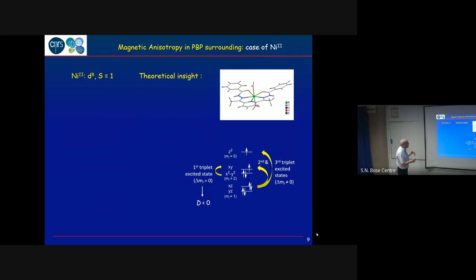Let's take just a few examples to illustrate that. For instance, if you take nickel(II), which is d8, if you fill the orbitals, you get something like that, and you reach a situation where you have two orbitals very close in energy that share 3 electrons. The anisotropy from zero field splitting comes from the excited states. The first excited state for such a system is when you promote one electron from this orbital to the closest orbital, this one. During this process, the ML is not changed. So the contribution of the first excited state to the zero field splitting will be negative.